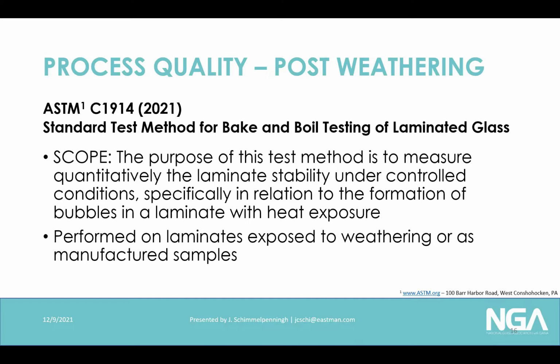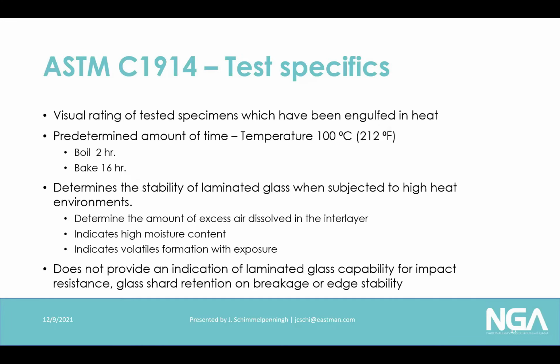You can perform this test on laminates exposed to weathering. So if you put something in an accelerated chamber or products come back from natural exposure, you can run these tests on those to see how they do. And so it can be run on weathered samples as well as samples coming off the manufacturing line. It is a visual rating after you subject the samples to heat. The heat can come in two ways. It's at 100 degrees C, 212 F.